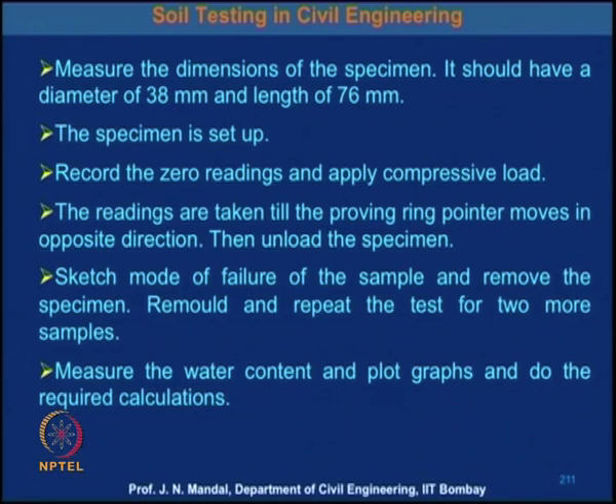The specimen is set up, record the 0 reading and apply the compressive load. The readings are taken till the proving ring pointer moves in the opposite direction. Then unload the specimen, sketch the mode of failure of the sample and remove the specimen. Remold and repeat the test for 2 more samples. Measure the water content and plot the graph and do the required calculation.